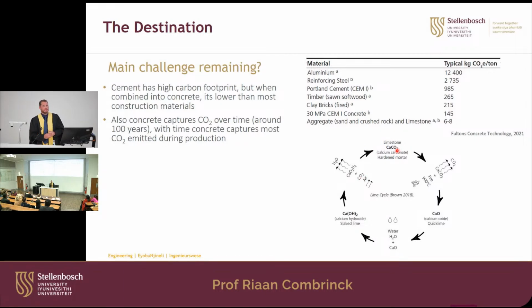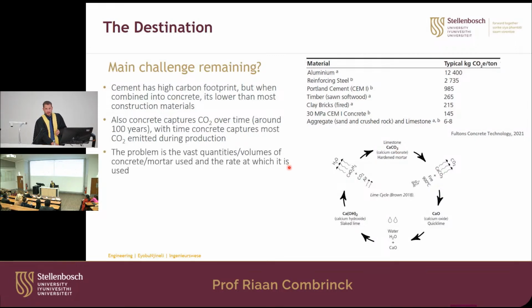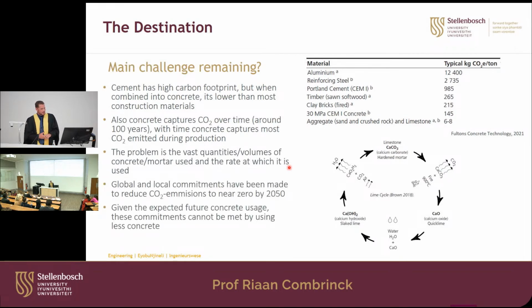So the problem is that we are not giving concrete enough time to reabsorb this CO2, and we are using too much of it too quickly because we need so much. So that is the big problem. Concrete's biggest problem is that we use so much of it, and now because of the big volume that we are using, it's giving out a lot of CO2. So the problem is the vast quantities and volume and the rate that we use it. Global and local commitments have been made to reduce CO2 emissions for the cement industry to zero by 2050.